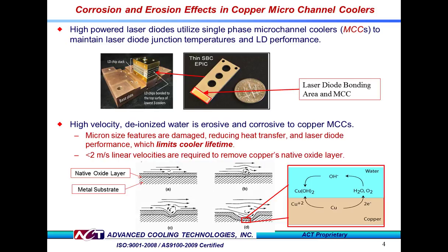Let's examine the problem a little closer. As we just mentioned, the laser diodes are cooled by a single-phase coolant, typically DI water. The laser diodes are usually stacked, as can be seen in the figure on the left, with the diodes mounted on the microchannel cooler. The high velocity flow rate of the DI water is erosive and corrosive to the base copper material.